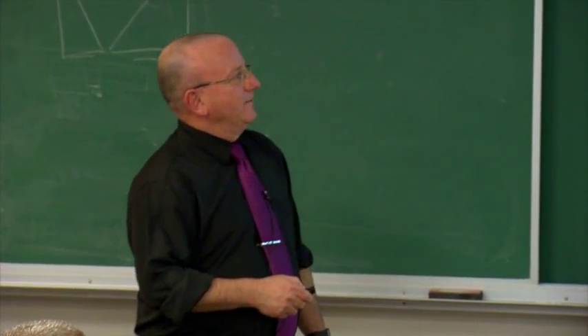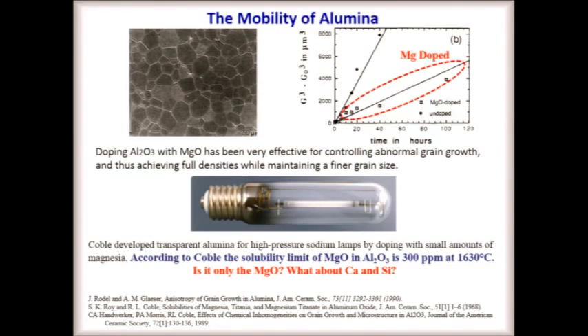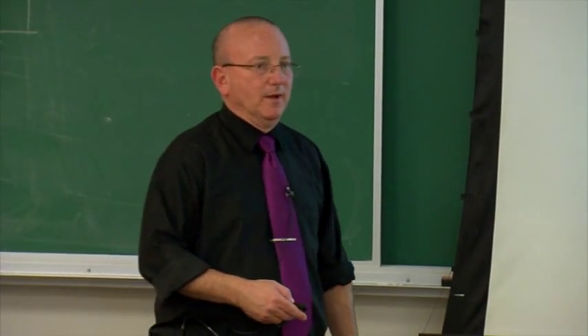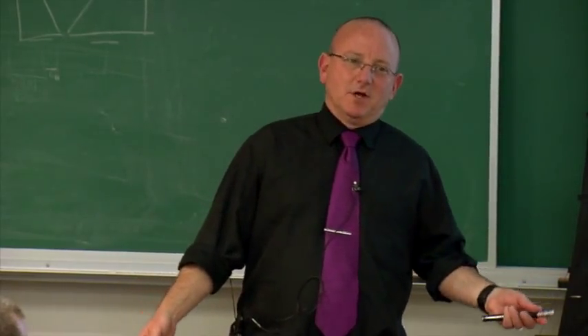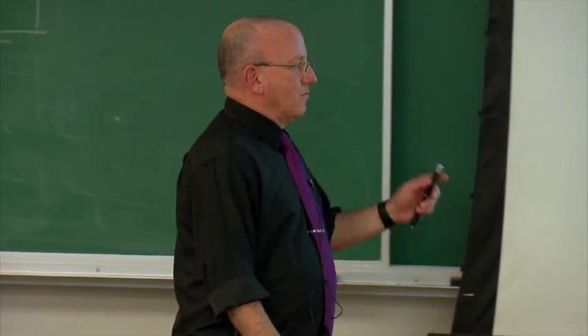And of course, Arthur was right. And this is the influence, some measurements from the literature on, this is to the power of 3, but it doesn't matter, showing the influence of magnesium doping on the grain size. So we all know that it's there. But of course, the argument is, well, it's not really the magnesia at the grain boundaries. It's precipitates of spinel, which are dragging the grain boundaries. And it's a problem, because we don't really know if there is precipitation there or not, because it's just at the borderline of the solubility limit. Oh, wait a minute. Actually, we don't know the solubility limit, or we didn't. And that was one of the problems.